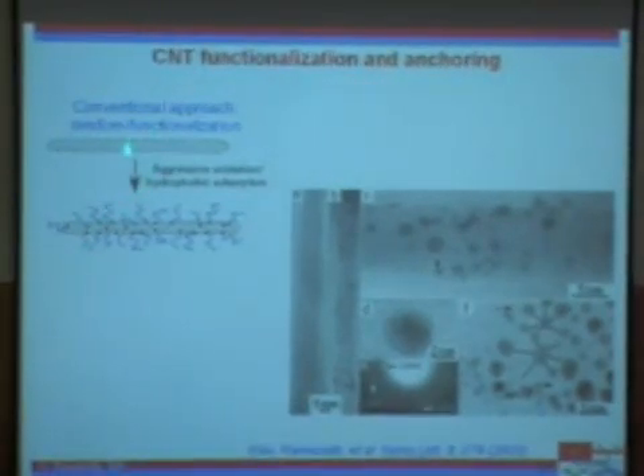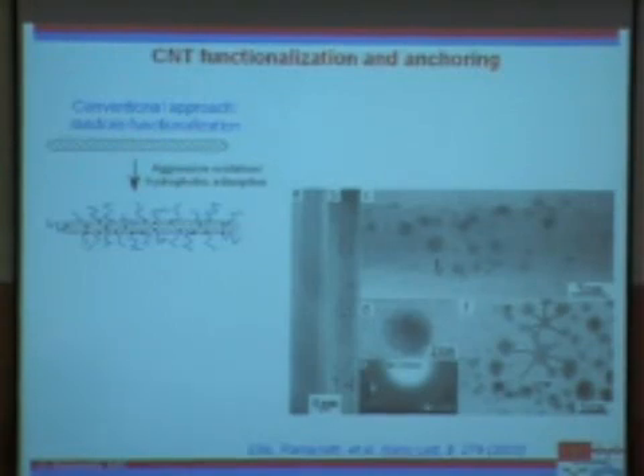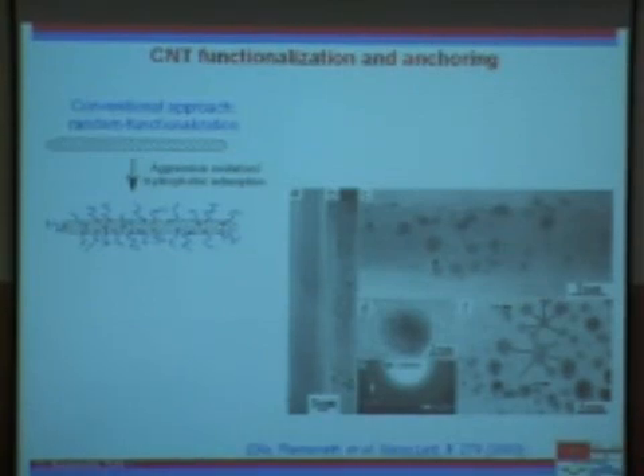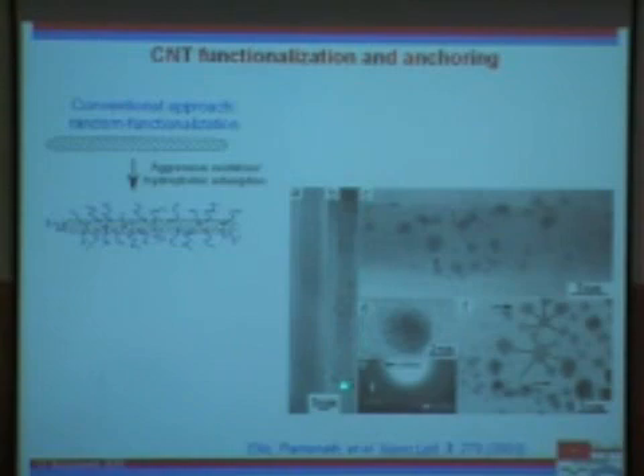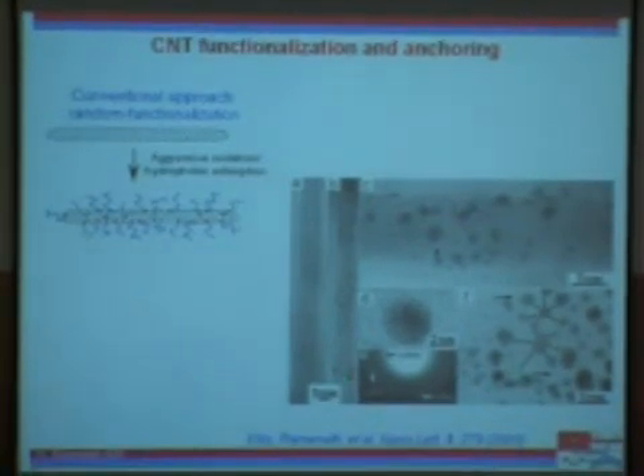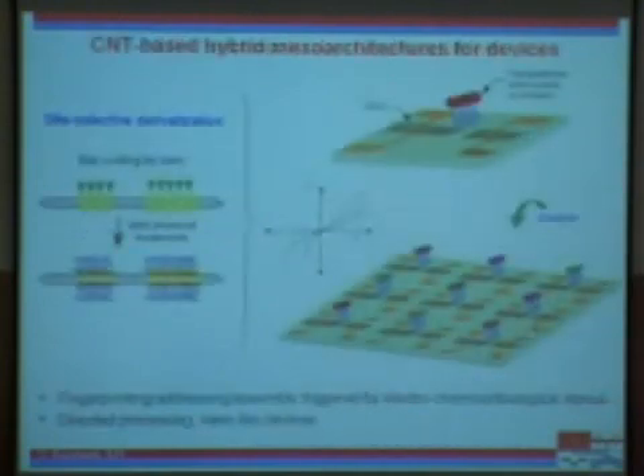Now, in order to interface those with other materials is difficult. So the typical strategy that is undertaken is to take this, beat the hell out of it in an acid, and then hope that bonds are broken, then attach other things to it. It works, as you can see here, gold nanoparticles decorating the carbon nanotubes, but you have no control over where this happens. So in order to make a device, you want to be able to do things precisely.